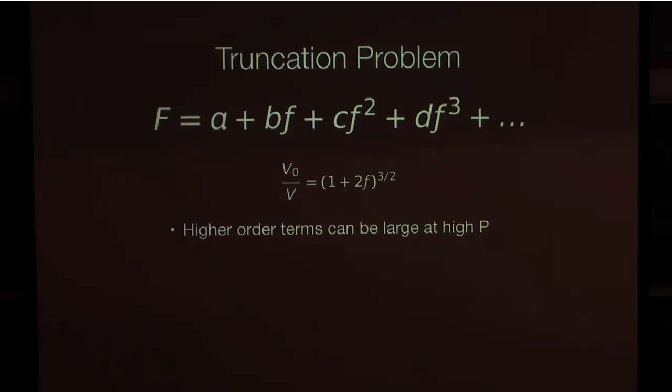One more question. Is it true that for most silicate material, K0 prime is close to 4? So the K prime 0. Yes, in that sense the third order and second order are almost the same for silicate material. But there are people who don't know much about this history, and they ended up using K prime equals 4 for, for example, very soft materials like ice. So that brings you an interesting question: you want to know a little bit about what's in the background and assumptions as well.